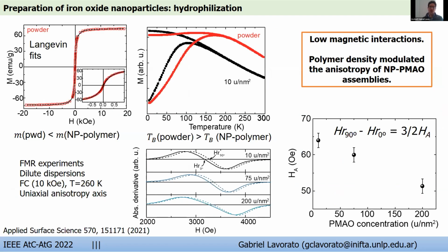So at this point, we wondered how these nanoparticle polymer assemblies are affecting the magnetic properties of the colloid. So a first comparison of the apparent magnetic moment and the blocking temperatures of the nanoparticle powder without polymer reveals that the magnetic interactions in the polymer assemblies are indeed much lower as a result of the larger particle separation compared to the powder without polymer. So we also performed ferromagnetic resonance experiments, and the difference between the resonant field in the parallel or perpendicular directions revealed small variations in the anisotropy of this colloid for different polymer concentrations, that is slightly higher for lower density of the polymer, and this is probably due to the assemblies formed by a large number of particles in the case of low polymer concentrations.